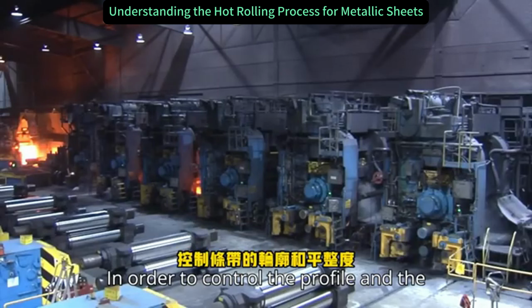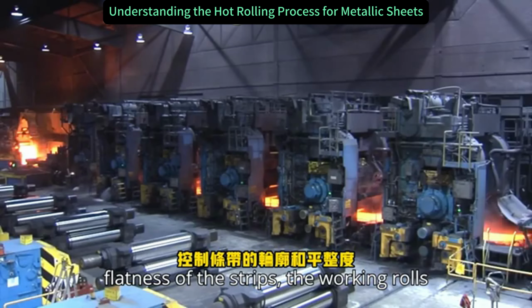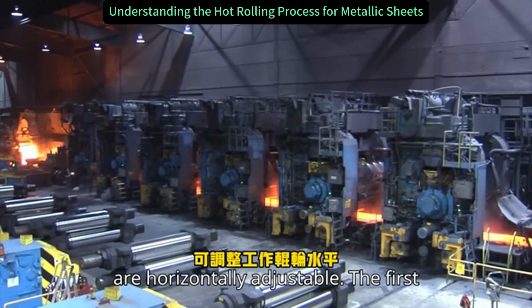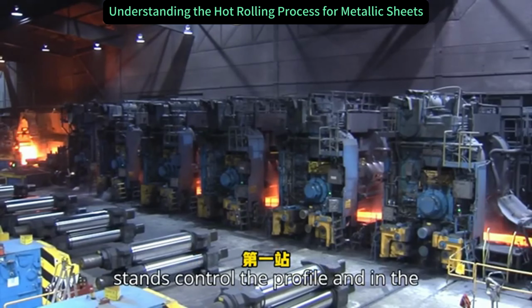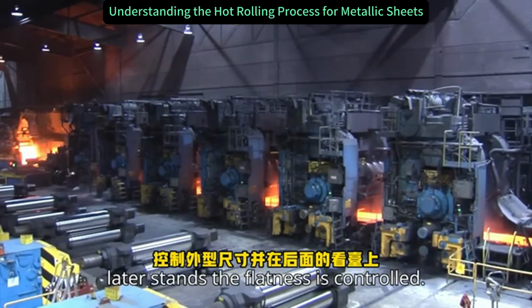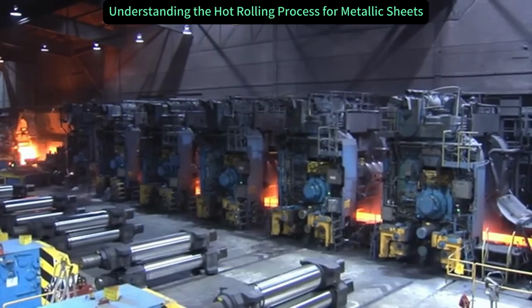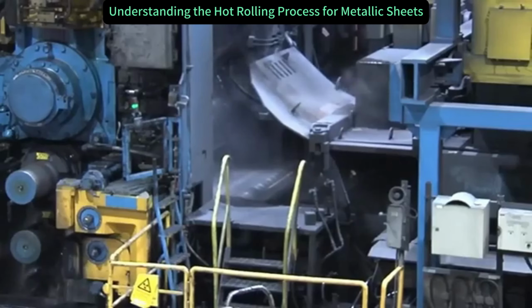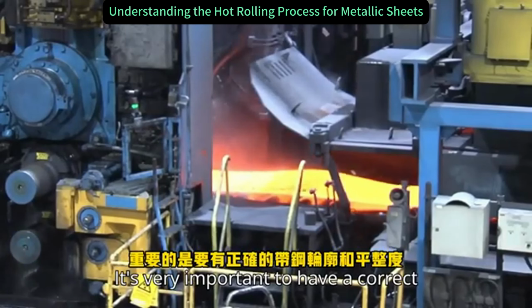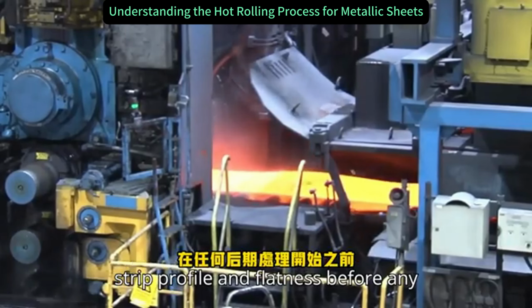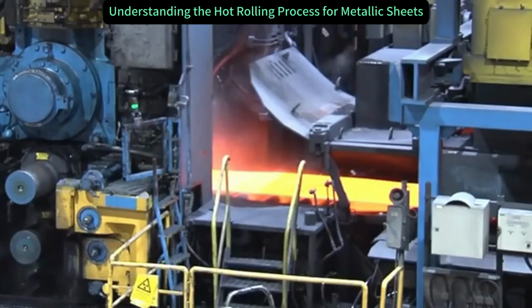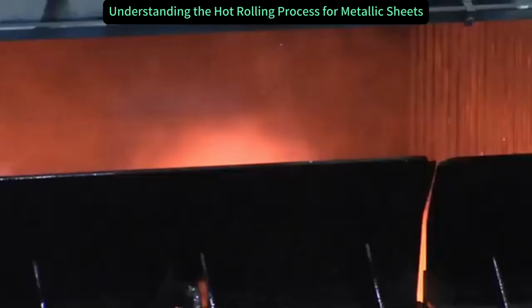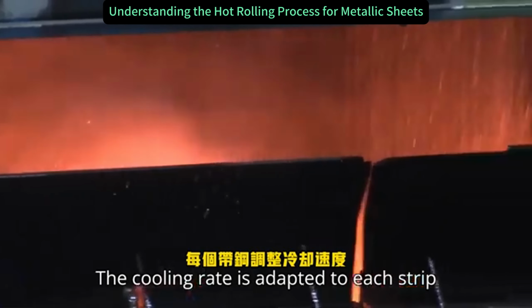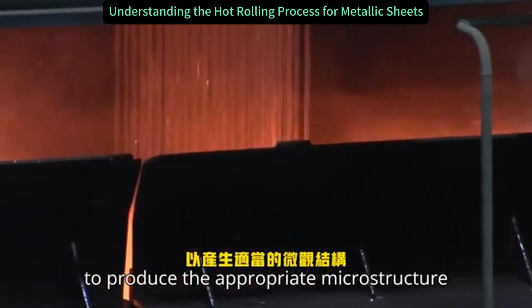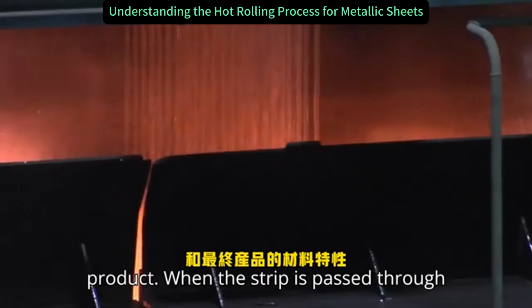In order to control the profile and the flatness of the strips, the working rolls are horizontally adjustable. The first stands control the profile and in the later stands the flatness is controlled. It's very important to have a correct strip profile and flatness before any post-processing starts. The cooling rate is adapted to each strip to produce the appropriate microstructure and material properties of the end product.